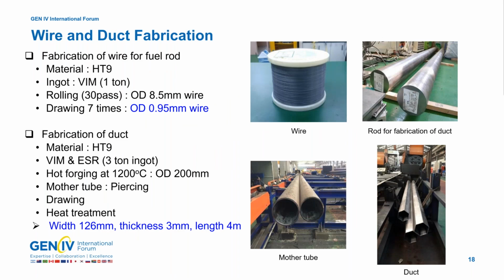This one shows fuel rod wire and fuel assembly duct. It's made from HT9. For the wire, about 1 ton ingots went through rolling and drawing, and this wire was fabricated. And for the duct, it's tough work to fabricate a long hexagonal duct. So from 3 tons of ingots through this process, forging, piercing, drawing, and heat treatment, we finally succeeded to fabricate this duct, with a thickness of 3 millimeters to meet the specification, especially the uniform thickness and straightness of this duct.